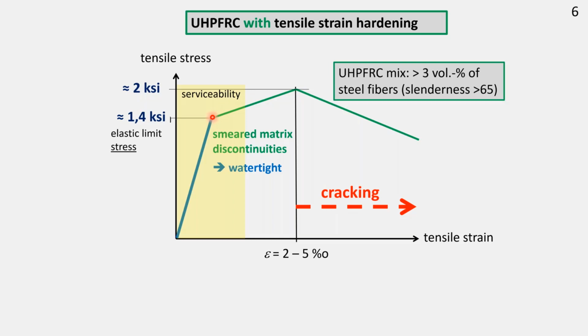But our tests showed that in this domain, the material is watertight. That's very important for application. Cracking, in the understanding of reinforced concrete, occurs only when we have arrived at the uniaxial tensile strength, at strains larger than 2 per mil.